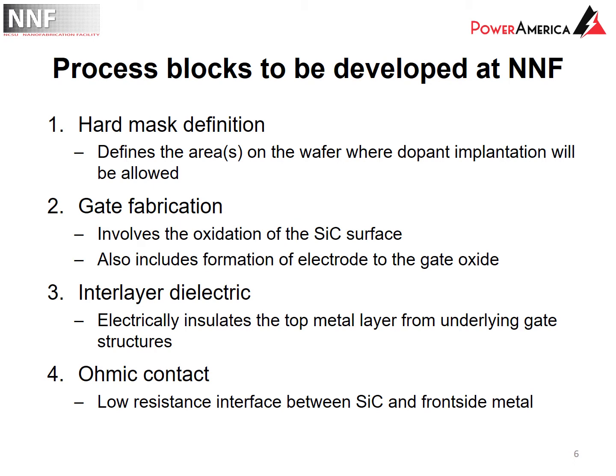The specific process blocks that we developed at NNF were the definition of a hard mask for ion implant, the fabrication of a gate along with the electrode to that gate, an interlayer dielectric which electrically insulates the top metal layer from underlying gate structures, and ohmic contacts to the silicon carbide.